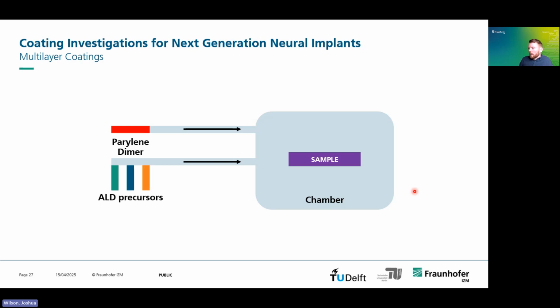So for example, we can put our sample in this chamber. What we have at IZM is a combined Parylene and ALD system. So we can deposit Parylene, and then we can deposit these ALD films. So ALD is atomic layer deposition. These are nanometer thin films. They are, as the name suggests, deposited effectively atom by atom. You would deposit a metal layer, then an oxide layer if you were making a metal oxide, and you slowly build it up like this.